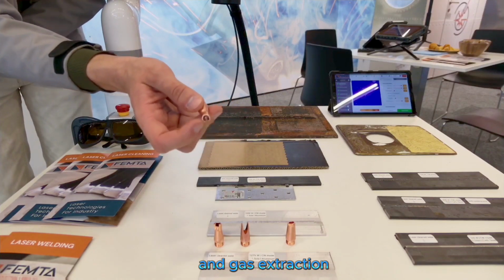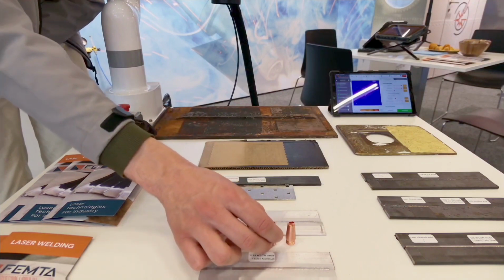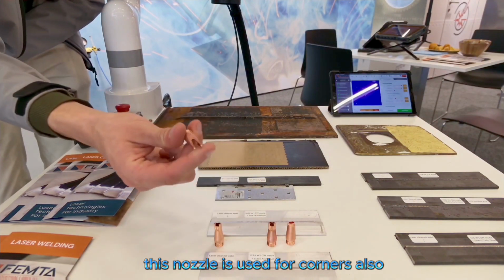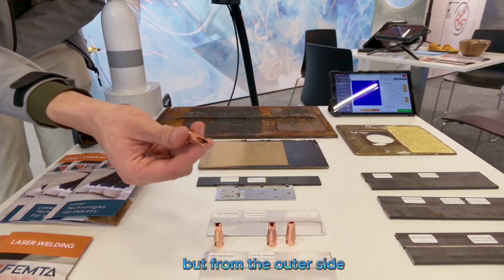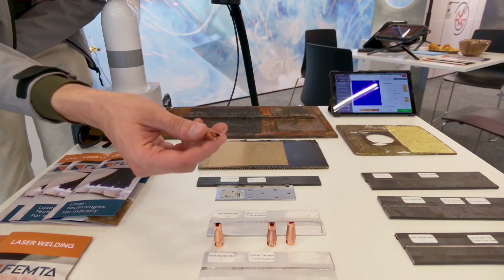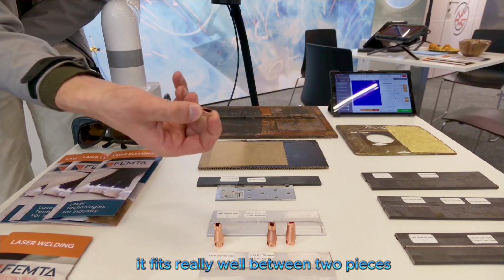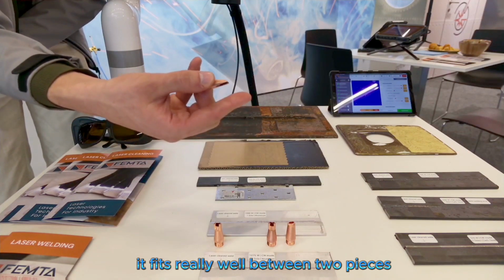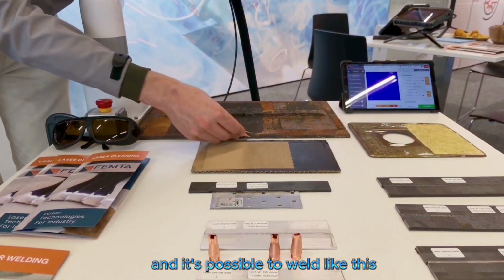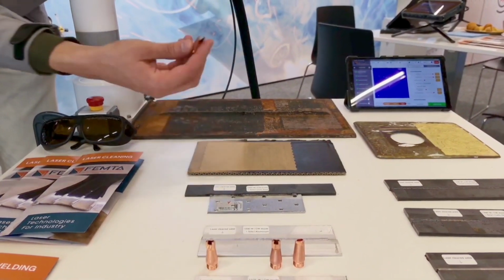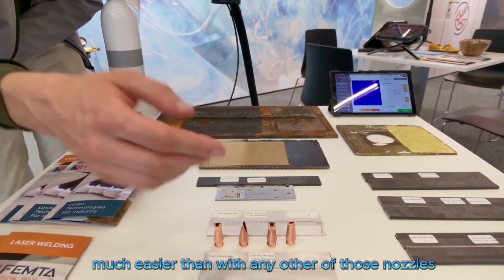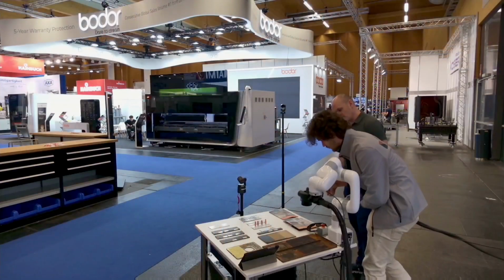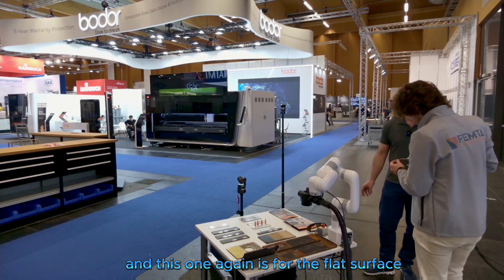gas extraction tip. This nozzle is used for corners also, but from the outer side. So it fits really well between two pieces, and it's possible to weld like this, much easier than with any other of those nozzles. And this one, again, is for the flat surface.